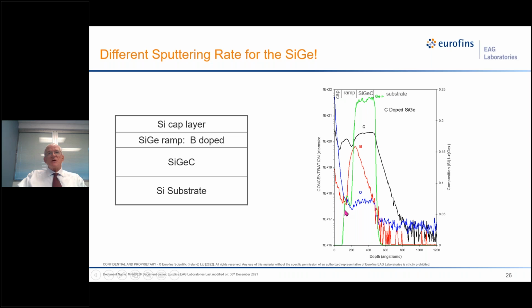Likewise, this boron is undoubtedly not real. If you have any sample out in air and expose it to room air, the surface will get contaminated with about the mid 10 to the 12 per square centimeter of boron, always. So that's probably, well, undoubtedly, that's an artifact.